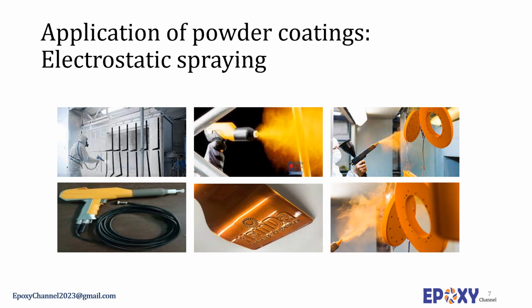Electrostatic powder spraying has good throwing power. Although the primary transfer efficiency is low, for example 50% due to the Faraday effect, the oversprayed powder can readily be recycled in the cabins. Recycling results in 95% overall transfer efficiency, which is the highest among the suitable paint systems. In this process, contamination of the powder in the cabins has to be prevented, because if it happens, there is no way to clean the powder again. Moreover, considerable effort is required when the paint color is changed, as the complete cleaning of the powder spraying booth is quite hard.